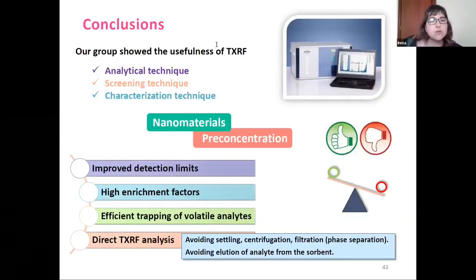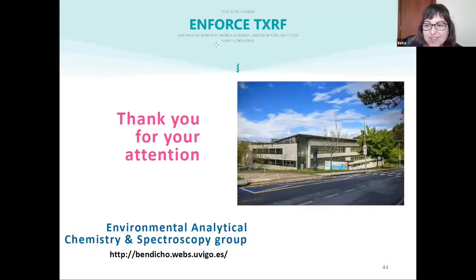Finally, in our group, we show the usefulness of TXRF as an analytical technique, but also as a screening technique at the beginning of the procedure and also at the end of the procedures for the characterization. Thus, the combination of nanomaterials for preconcentration strategies allows us to improve the detection limits, obtain high enrichment factors, and also trap the volatile analytes. Since TXRF allows the direct analysis of suspensions on membranes, we avoid the settling, centrifugation, and filtration steps for phase separation, and also we avoid elution of the analyte from the sorbent. That's all, and thank you for your attention.